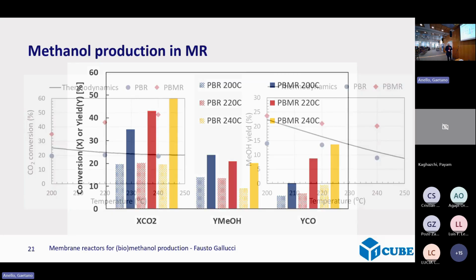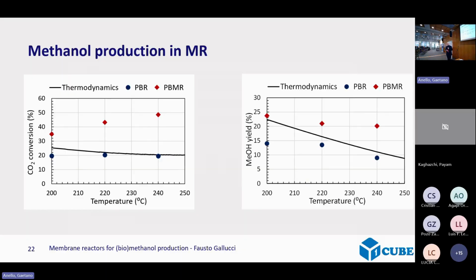So here you see other experiments where there is the equilibrium. You see that the catalyst is quite good, because in a packed bed we reach the equilibrium, and in the packed bed membrane reactor we go well beyond the equilibrium. Of course, it's the equilibrium for the conventional reactor. Because once I brought a proposal and I was crushed because they told me that I cannot go beyond the equilibrium. So this equilibrium is only for the conventional reactor.